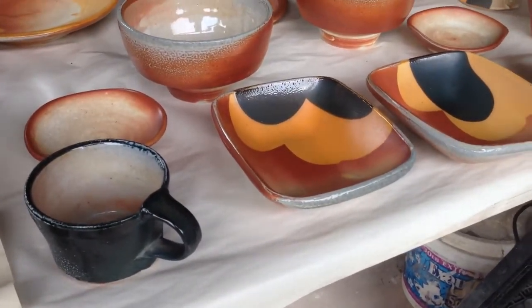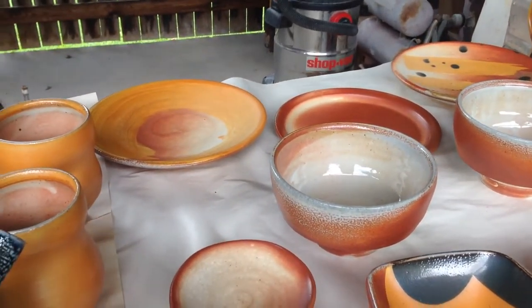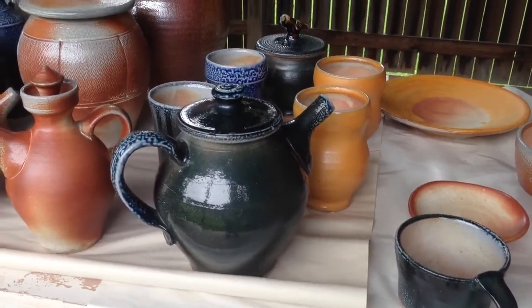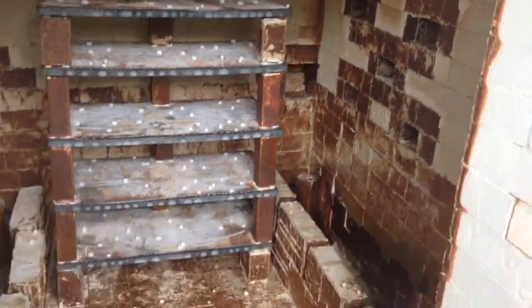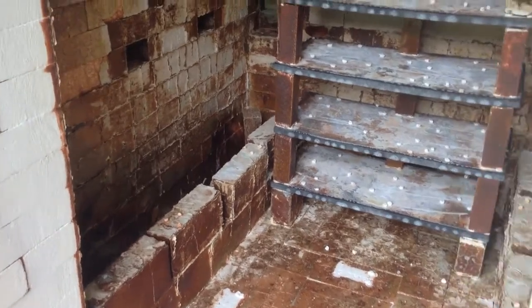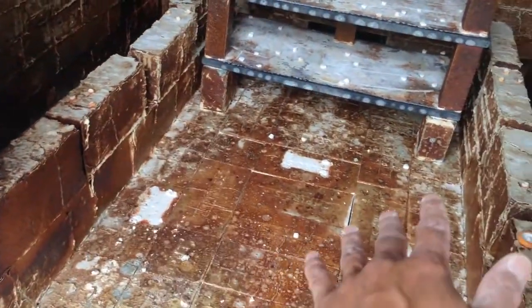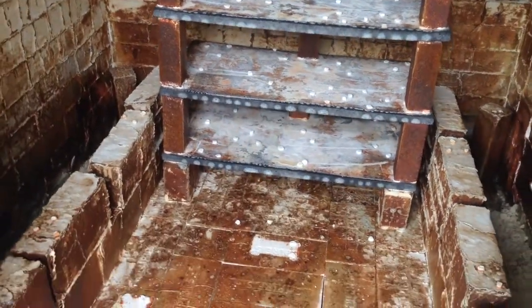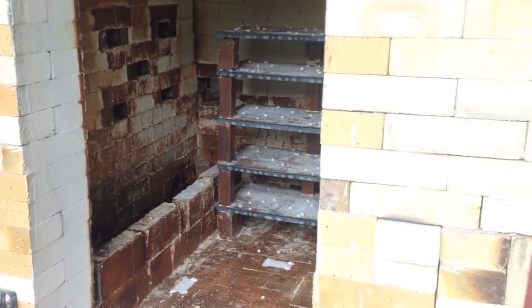This solid method would probably work better in a smaller kiln, maybe with burners opposed to each other — firing in from the sides, diagonally, or from the front and back. My burners just come in from the back. What happened was when I dumped that mixture into the fireboxes, it got pushed toward the front and a lot of it came through the bottom shelves, then circulated and went out the flue. So the bottom really got hammered, and the rest wasn't as well covered. A different kiln design would certainly give different results.